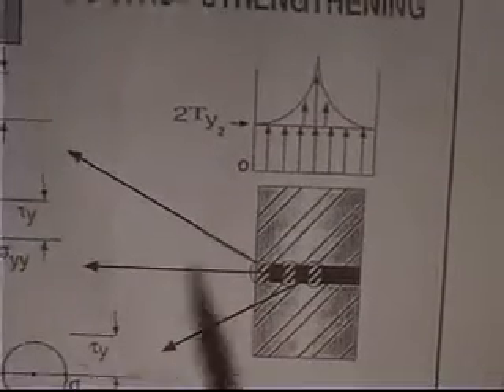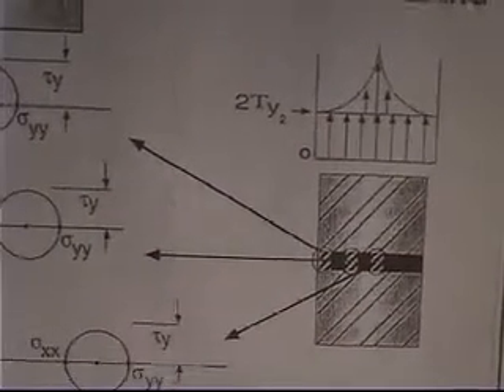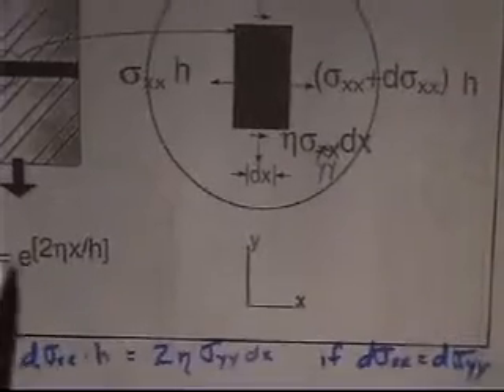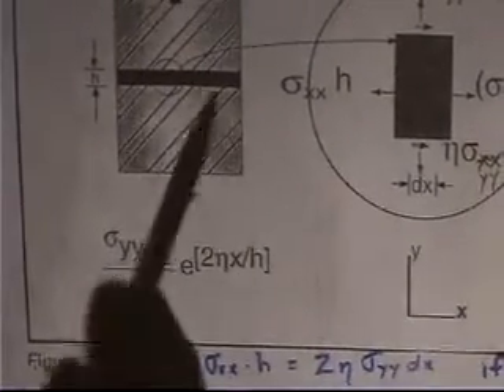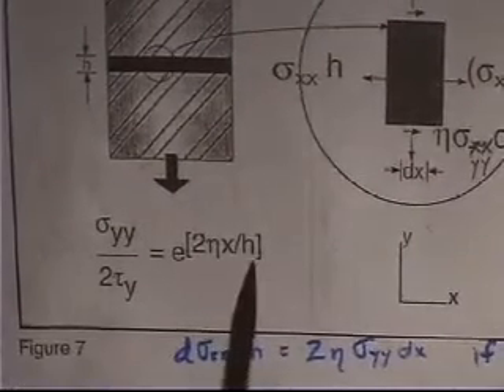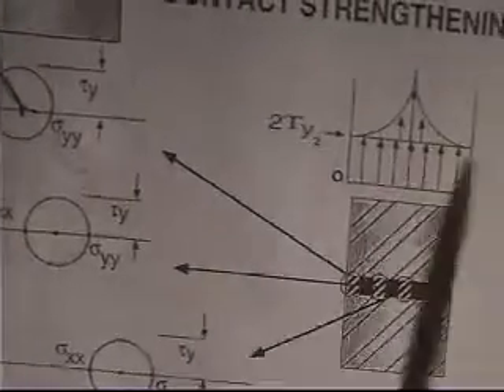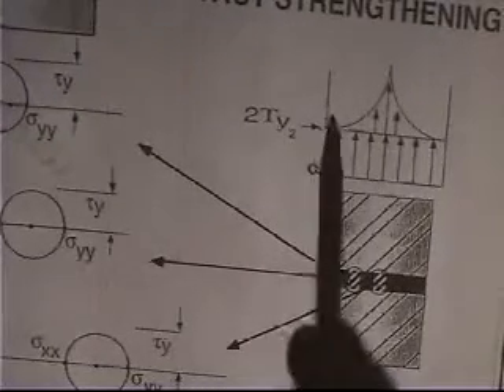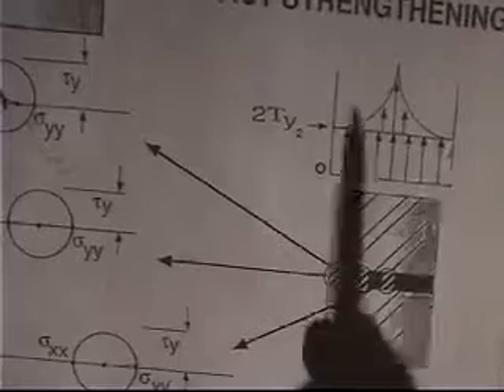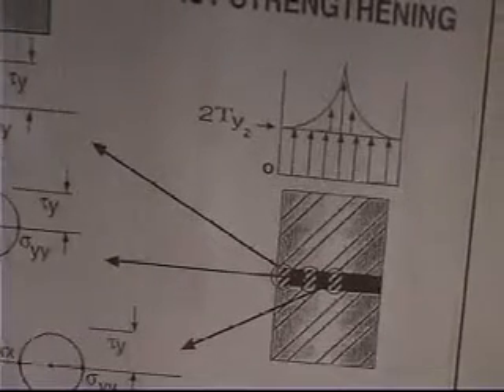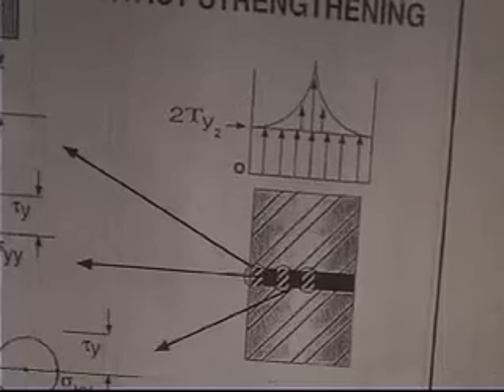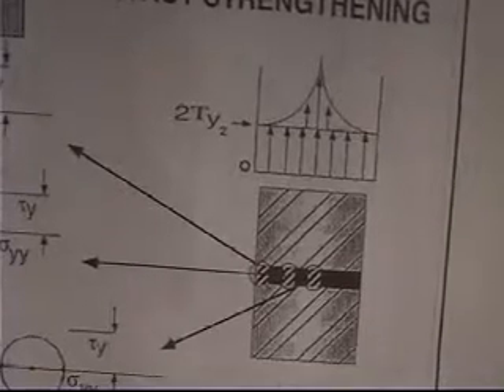It turns out that the proportionality is exponential of x over h, where x over h is a width to thickness ratio. The thinner the value of h, the greater the strength of this joint, the higher this hill of triaxial stress is. And the actual yield strength of the material is not this value, but the average value across this whole thing. And so you get what's called constraint strengthening. Physically, all it means is the material in the very thin joint can't yield because it's constrained by the non-yielding base material on either side. And it gives you a constraint strengthening.